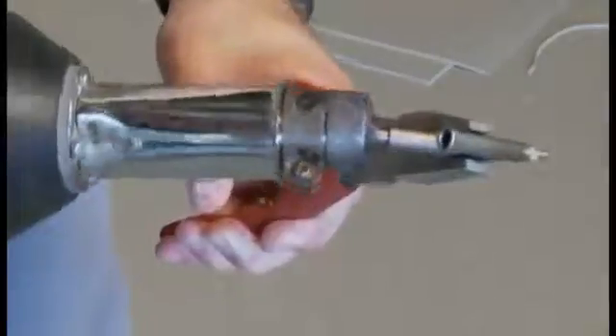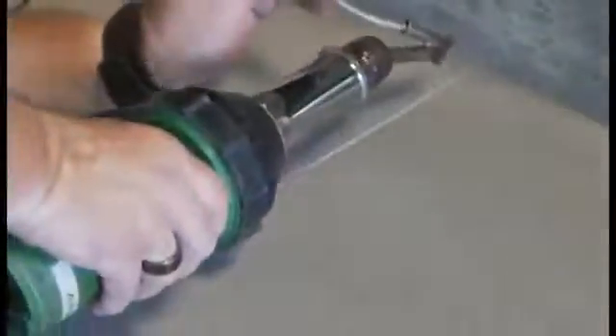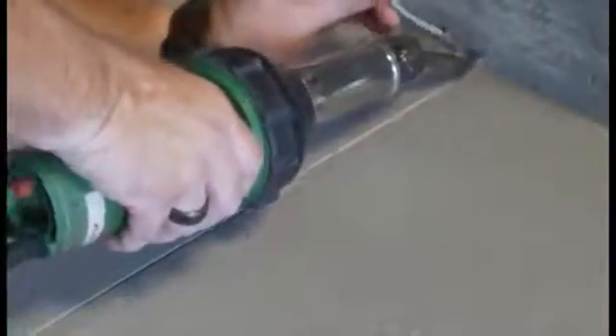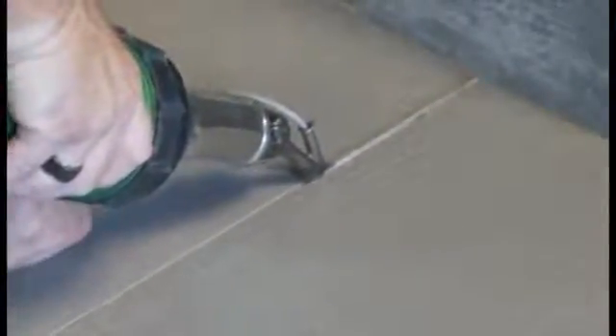After the heat gun has been preheated, attach the nozzle. Starting with a cold nozzle will prevent softening of the weld rod as it passes through the nozzle and will make tear-offs less likely also. Practice welding on a piece of scrap material before starting your first job to determine the proper speed and adjust for the higher temperature setting.